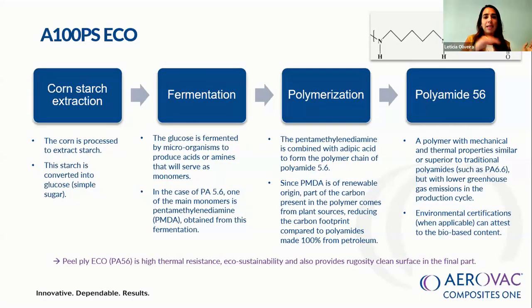In the case of polyamide 5/6, we have a special monomer that we name PMDA. And this PMDA, when combined with a diacid, will form a polymer chain. So as the PMDA is of renewable origin, part of a plant source, it reduces your carbon footprint. This is the important part for bio-based. You decrease your carbon footprint. And polyamide 5/6 has really good mechanical and thermal properties, really similar to what you see in the market for polyamide 6 and 6/6, and it is also able to be certified and tested for the bio-based content.